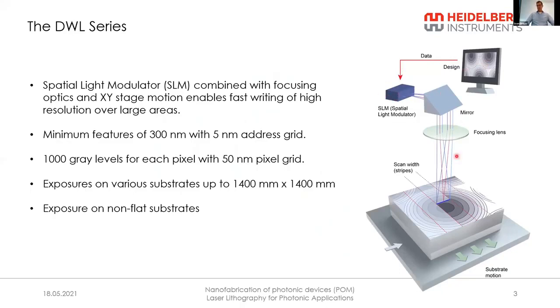The image is focused onto the substrate. In this case, it's a line of pixels, and the stage system moves the substrate underneath this focused image. And we raster scan the entire surface of the substrate. It has the big advantage that the quality and fidelity of the structures is very high, the position accuracy is very good, and the write time does not depend on the number or shape of structures. Basically it depends only on the overall area and the resist properties of the substrate.